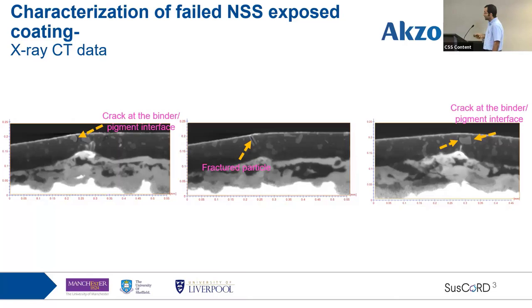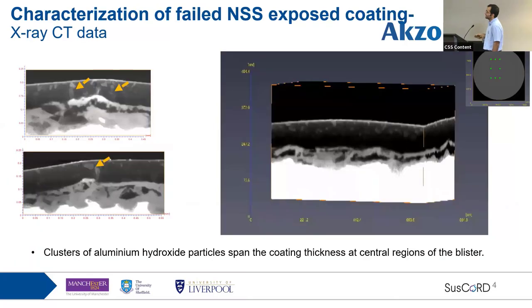So we cannot rule out that these are the cause of the failure, but what I'm actually more interested in is the formation of these elongated clusters of particles within the coating. I actually believe that the interfaces of these are weak and will allow the transport of the environment along this interface.